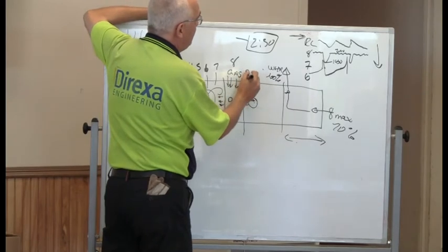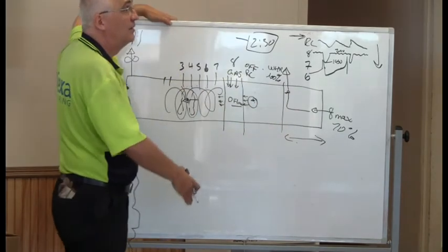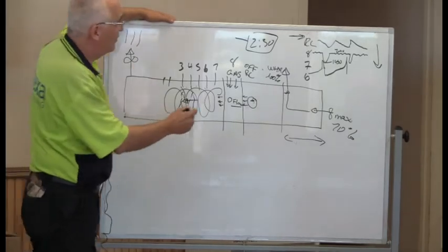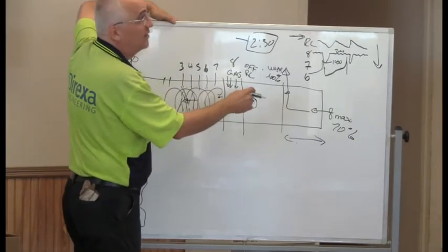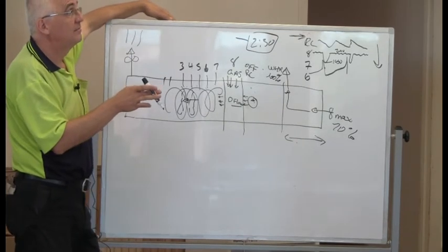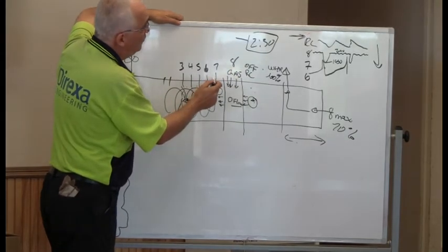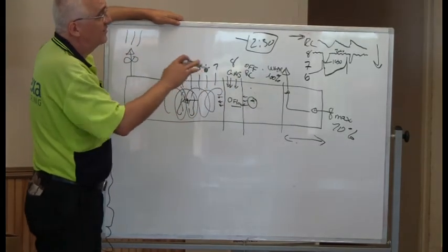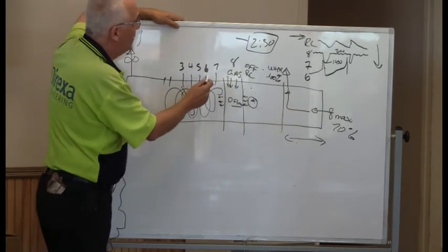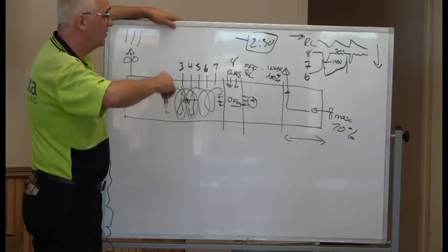Rapid cooling is off for sure, because I don't want that to go on and off, creating a quantity of air which is going to add up here. You don't want things to start cycling, moving. For me, flashing is off. The closest one is probably off, so it doesn't mess with the flashing zone. And then in the following zone, the flashing starts, the gas goes on.